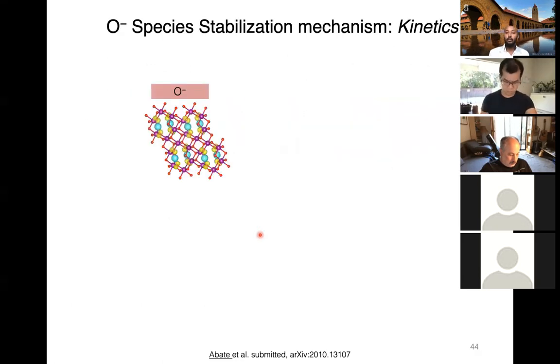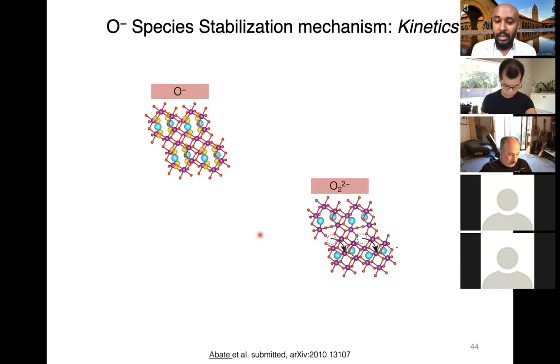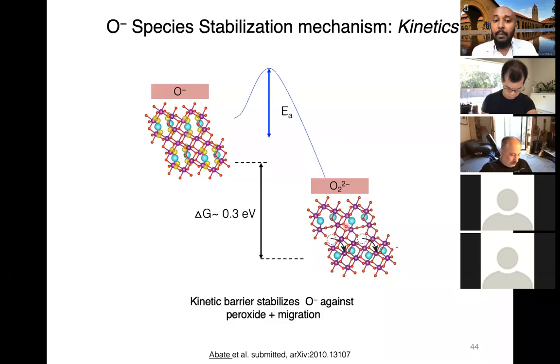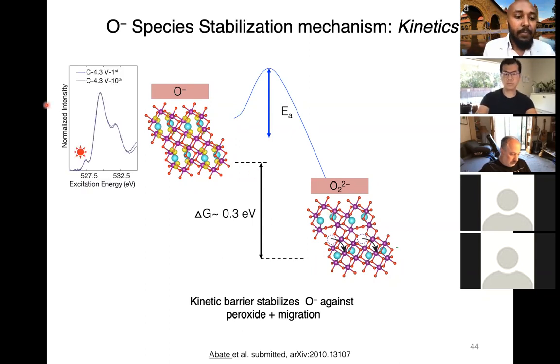We also compared the stability of the O- species with a peroxide and with a cationic disorder, as shown over here. So even though what we observe experimentally is the O- species, we found out that the peroxide system with the cationic disorder is actually more stable thermodynamically, but we don't observe it experimentally. And this explains that there's a kinetic barrier that actually prevents the O- species from forming the peroxide with cationic disorder. In fact, we confirmed this density calculation using an experiment where we see this pre-edge feature that we now confirm to be the O- species is stable and reversible for several cycles.